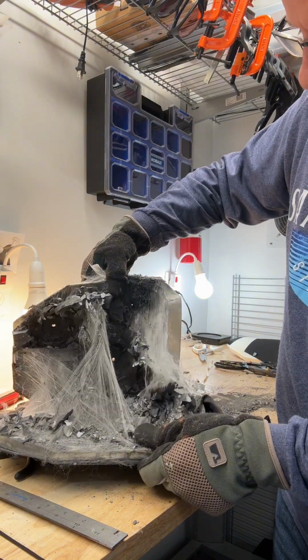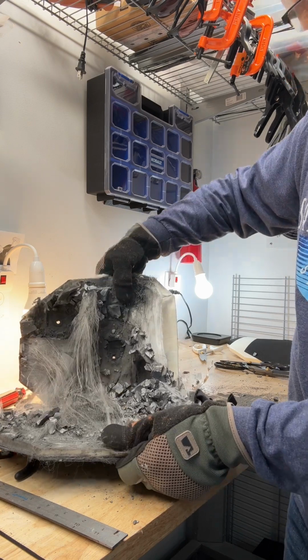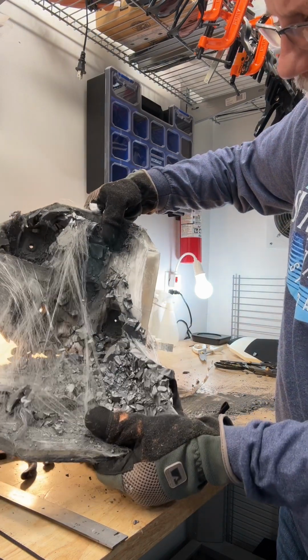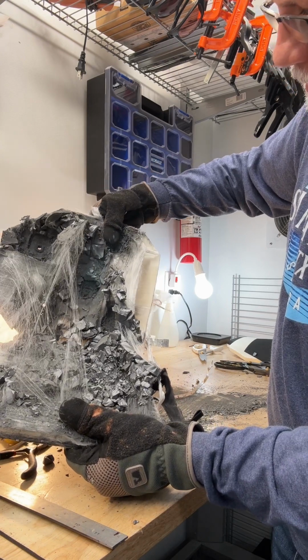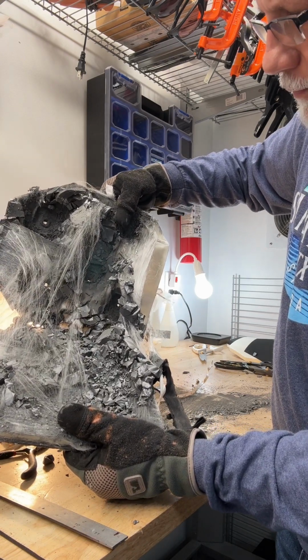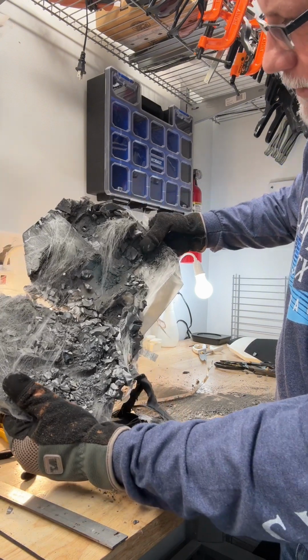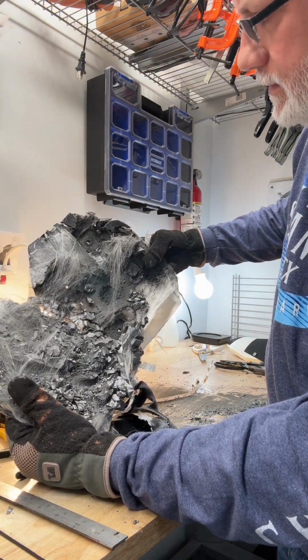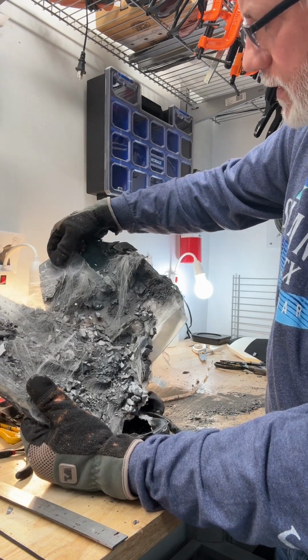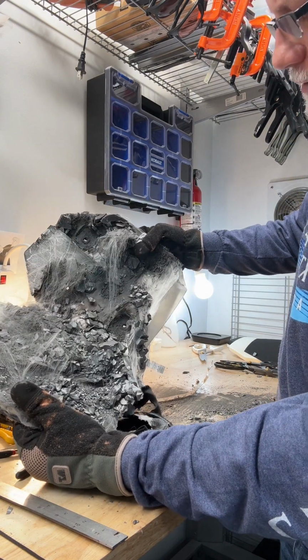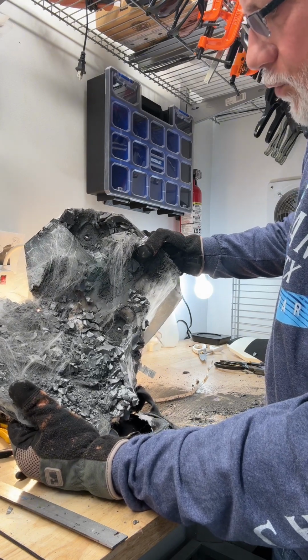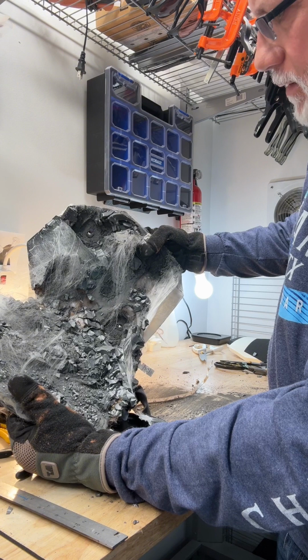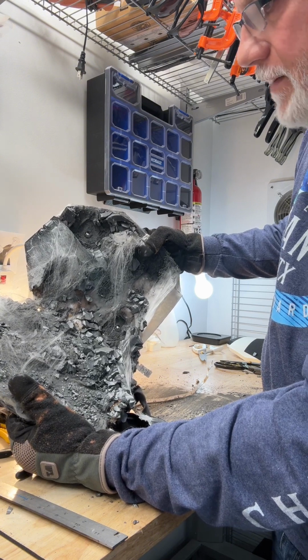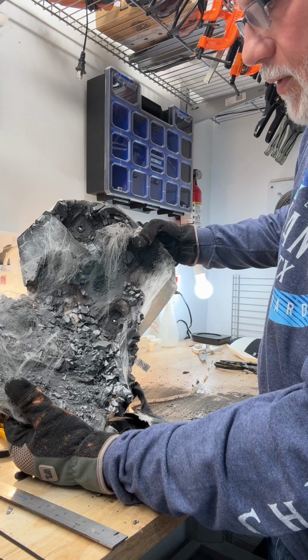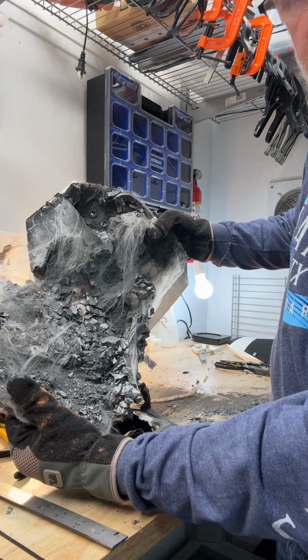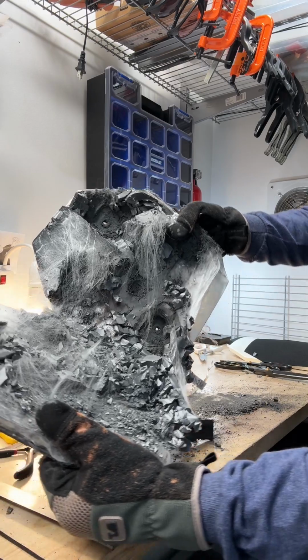But as you begin to pull this apart, you can also see the effect of 5 rounds of 30 caliber M2 AP going through a ceramic armor plate. So that's what's left. You've got a few chunks left, but not much. You've got a piece up here. Everything else is pretty much dust. And it was a very good performance given this reaction. It was extremely good performance to be able to stop 4 of those 5 armor piercing rounds with a monolithic plate with this type of performance. It's absolutely impressive.